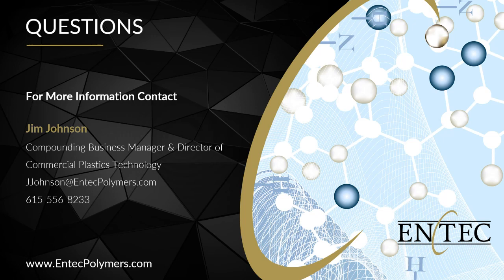Another question, do compatibilizers affect the recyclability of the polymer blend? Once again, in most cases, it will improve the recyclability in terms of allowing you to use that material and compatibilize any contamination or mixed polymers in there. Most of these products, if we think of, for example, an SEBS or an acrylate for a compatibilizer, are really not going to affect that recyclability. If we look at something like an MAH grafted material, let's say you're talking about polypropylene and nylon, the level of the MAH in there is very low when you incorporate it. And again, it's an olefinic backbone. So generally speaking, no, that should not affect the recyclability of that polymer blend.